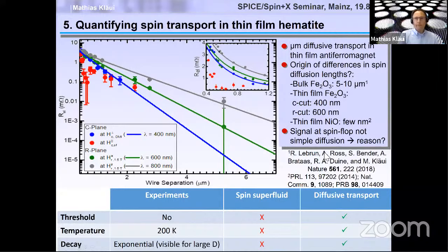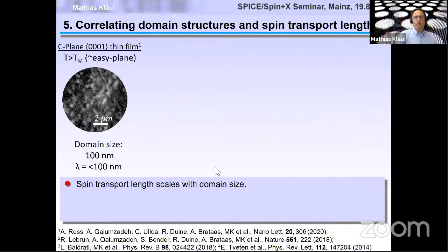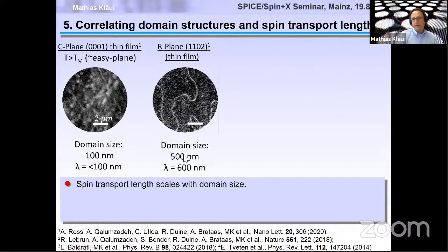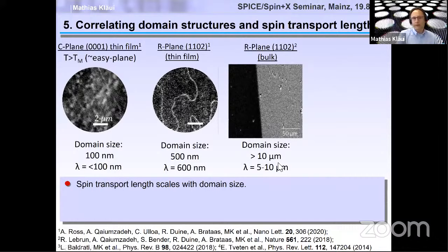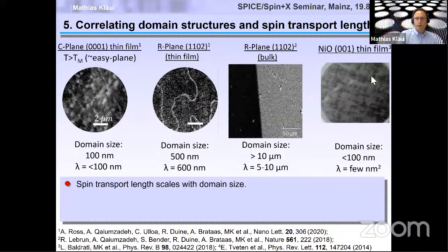And so to check that, we did some imaging, and we found that in the C-plane, where we see very short spin transport, we see very small domains with many domain walls. In this R-plane, where we see a transport length scale of the order of a few hundred nanometers, we also have domain sizes of a few hundred nanometers. And in the bulk, we have domain sizes which are tens of microns, and we see also micron-sized spin transport length scales. And also in nickel oxide, we see very small domains, and also very short spin transport length scales.